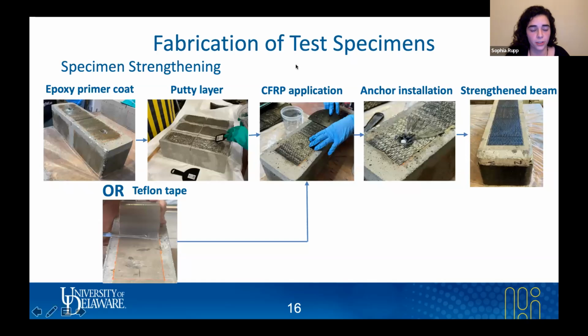And then comes the actual strengthening process. So I briefly touched on the first two steps here, but I'll summarize them again. In order to strengthen the beam, you first start with an initial neat epoxy primer coat, and then you apply that layer of putty epoxy on top, so long as you are strengthening a beam that includes that putty layer. If you are strengthening a beam where you skip that putty layer, you would then move on to the third step. And additionally, if you're fabricating or strengthening an unbonded beam, you would skip those first two steps and move on to just applying that Teflon tape,